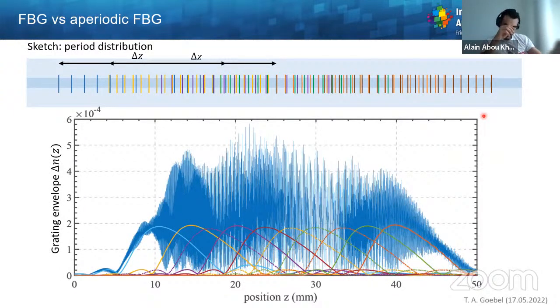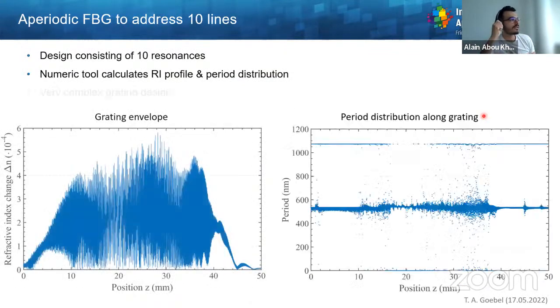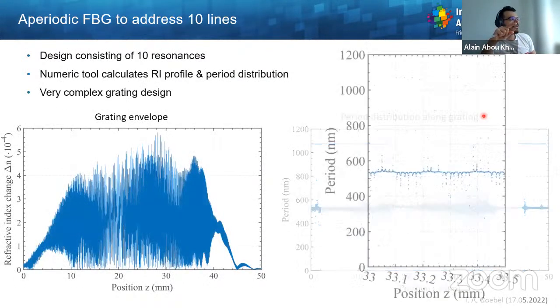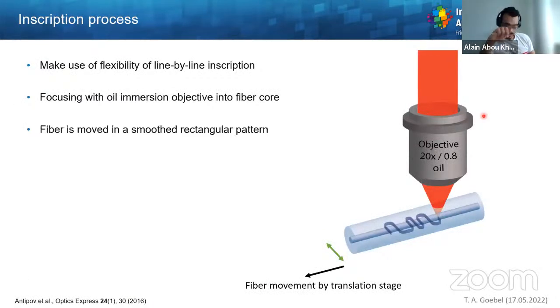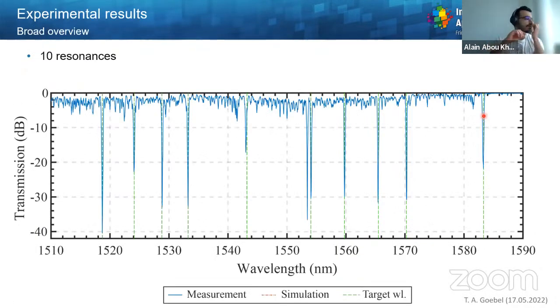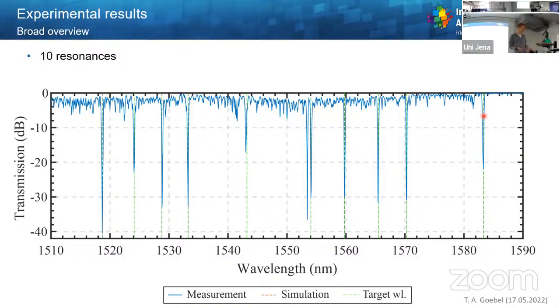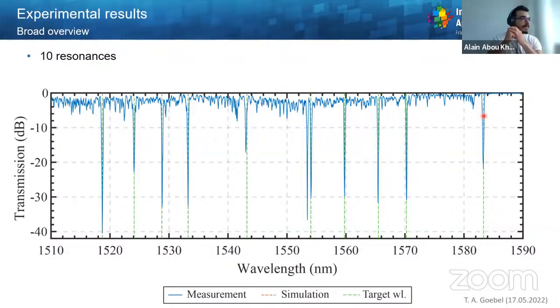Okay, and also at some point in the next step, you show the transmission depths. If you go to the next slide, I think, also continue. When you did the line by line, yep. If you continue, please, is when you have the transmission depth. Exactly. So here you have around 40 dB of transmission depths, very good transmission depths. So how long was this grating? This was 50 millimeter, the one I've shown you before. And line by line, you were assuming a periodicity, so it's a first order grating mostly. Yes, exactly, based on the first order. So using probably a green laser and doing line by line with oil objectives.